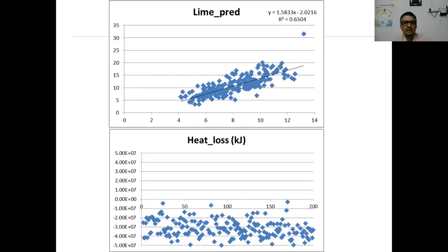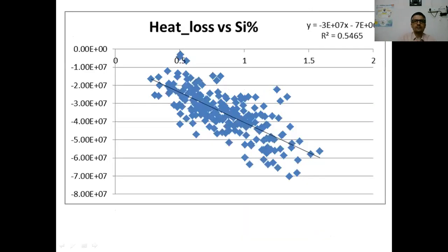As far as the heat loss calculations are concerned, we have got a lot of scatter for the heat loss, in terms of kilojoule values. Although there was a lot of scatter, if we plot the heat loss with respect to the silicon present in the hot metal, there is a band of error, but it is showing some relationship. That means that if the silicon is high in the hot metal, obviously it is going to generate a huge volume of slag. The larger the slag volume, the larger will be the surface area covered by the slag inside the converter, as well as along the lance, because the lance is also immersed into the slag. Since a larger surface area is covered by the slag for the high silicon content hot metal, there will be a larger amount of heat loss also.